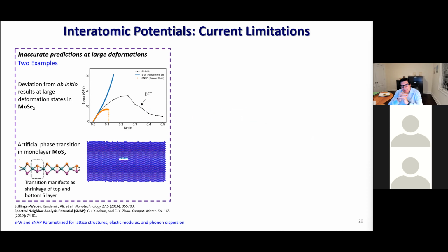And when we started, my group doesn't develop force fields, but we found that if you go to the literature and look for parameterized force fields for the material of interest, molybdenum diselenide, you get very weird results. So let me show two examples of what I mean by this. This is a DFT stress strain curve. I believe it was in the zigzag direction.